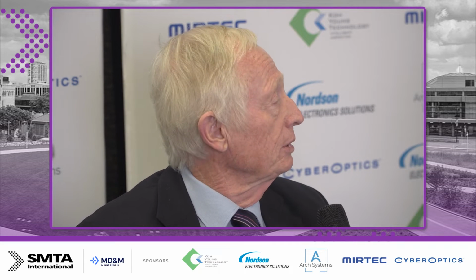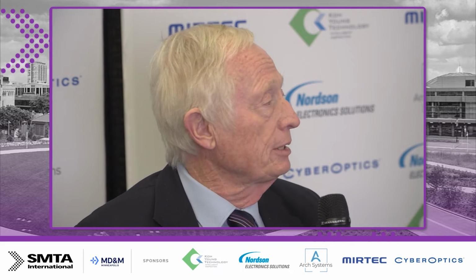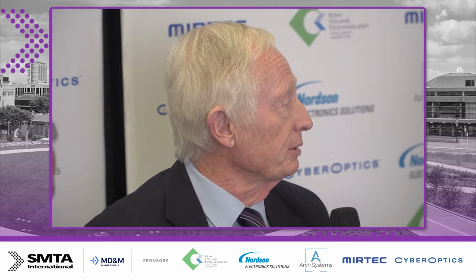And as you were saying, another thing you can do is break down the microstructure so that the bismuth phase is smaller or thinner or better dispersed, so that you don't have lumps of it that can crack and initiate failure. So there's a few tricks. I think adding things like silver really goes into reinforcing the matrix, because the bismuth is in a tin matrix, and you can make that tin matrix like a buffer that protects the bismuth phase from the stress that would otherwise crack it.